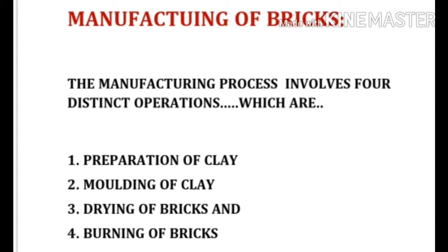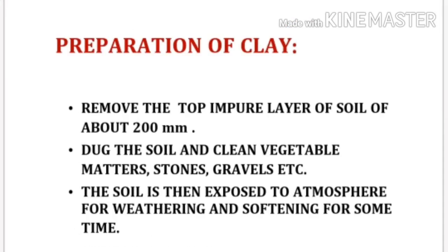Manufacturing of bricks involves four stages: preparation of clay, molding of clay, drying of bricks, and burning of bricks. For preparation of clay, the top layer of soil of about 200 mm thick is thrown away and rejected because top soil is full of impurities. Then the soil is exposed to the atmosphere for weathering and softening for some time.